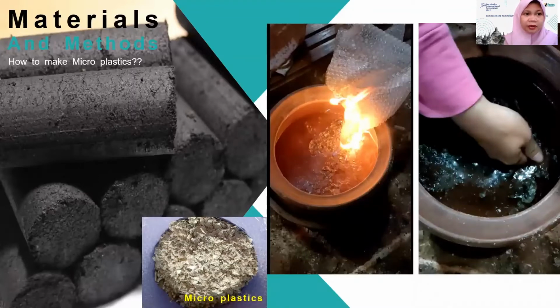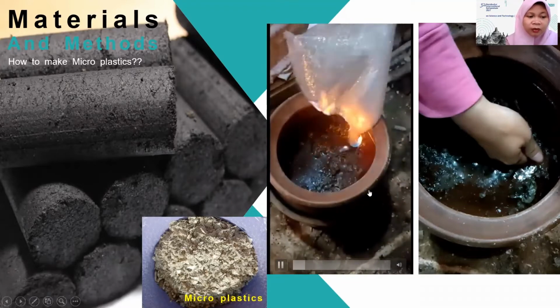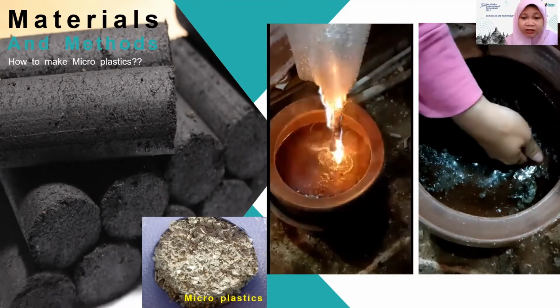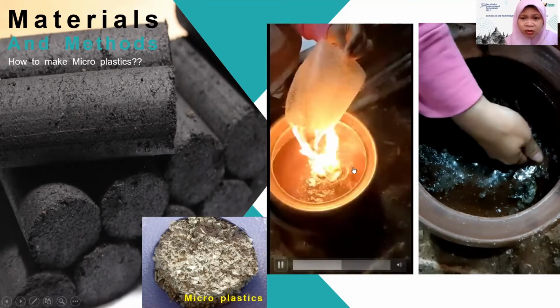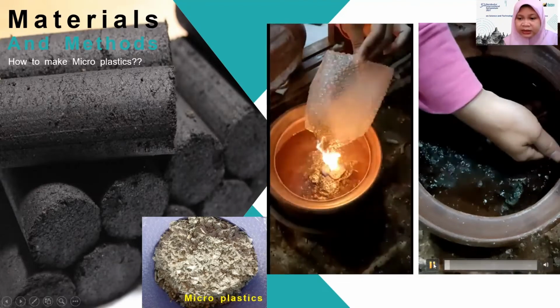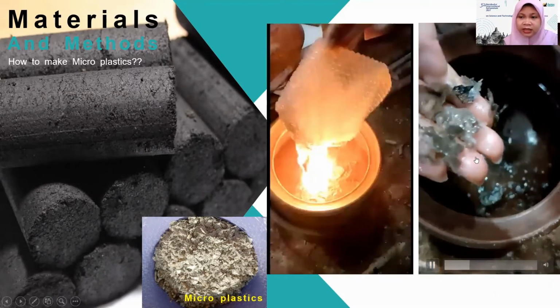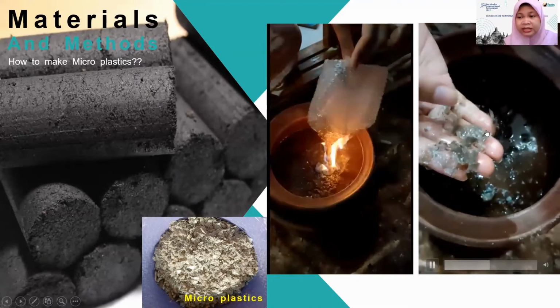Well, in this part, I'm going to tell you about the materials and methods, where I use three main ingredients for making the solid briquette. They are plastic, sawdust, and paper. The plastic was collected from the trash of orchid polybags, which are made from low-density polyethylene. Afterwards, the dried plastic was picked using tweezers, burned, and placed above a big bowl of water. The burning plastic will drip down into the bowl like small chips. So this is how the plastic is burned. But then at the end, we will receive something like this, like microplastic.